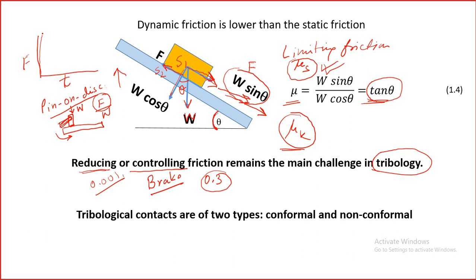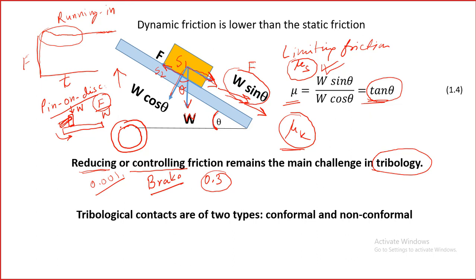As the disc rotates you can continuously with time measure the friction force. Normally if you plot time versus friction force, initially there will be some rise, it goes down, and at some point it will stabilize or fluctuate. Normally it takes some time before it stabilizes — this is known as running-in. The pin continuously moves on the same track — this is called multi-pass.